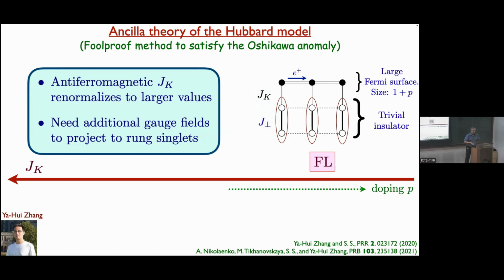Now, what I won't go into, and which is gone into in great detail in these papers, is that if you want it to really work when JPerp is small compared to JK, then you also need additional gauge fields to ensure the singlet projection and get rid of the extra degrees of freedom. I won't go into that because in the phase that we're interested in, those gauge fields are also Higgs. But near the transition, they become very important.